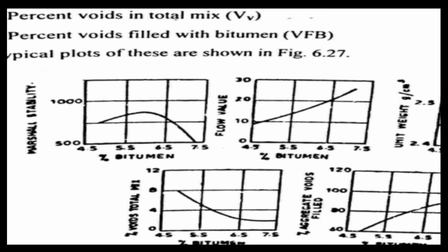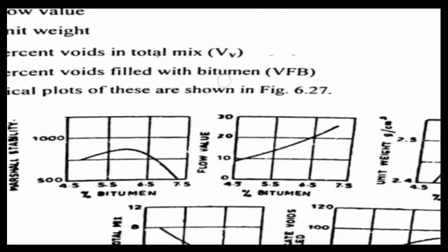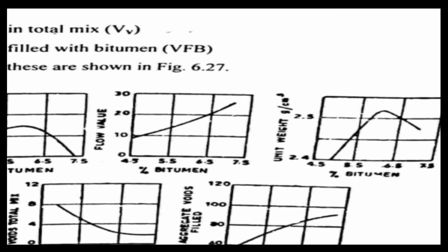In the second graph, if you observe the flow value, if there is an increase in the bitumen, it will help the aggregate mix sample to deform, as the increase in the bitumen will act as a lubricant in the concrete mix.